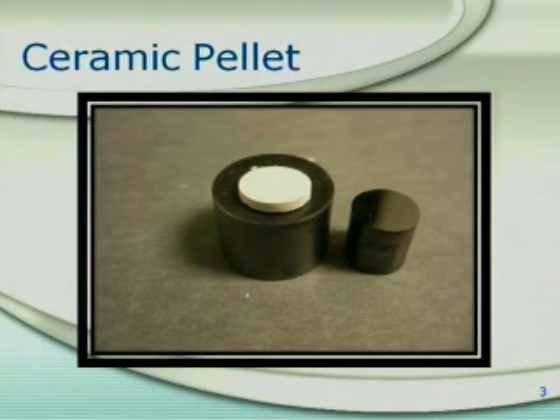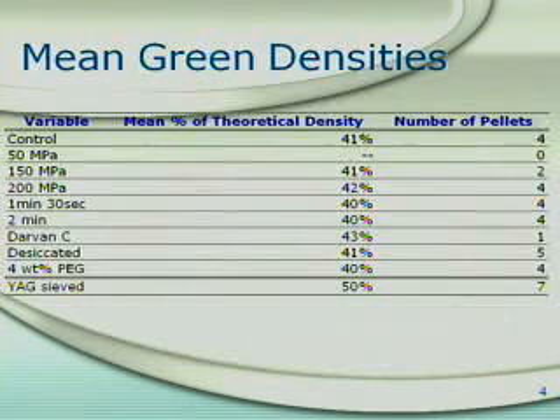I did a study over the summer to test different variables and determine their effects on the green densities. Variables I tested during the pressing of the powders are shown in this table. The results of the study are in terms of the mean green density that each variable had obtained, and the column on the far right shows how many of the 5 pellets made for each category remained after the final step. The 5 control pellets were made using about 100 megapascals of pressure for 1 minute with 2 weight % polyethylene glycol, or PEG, as a binder.